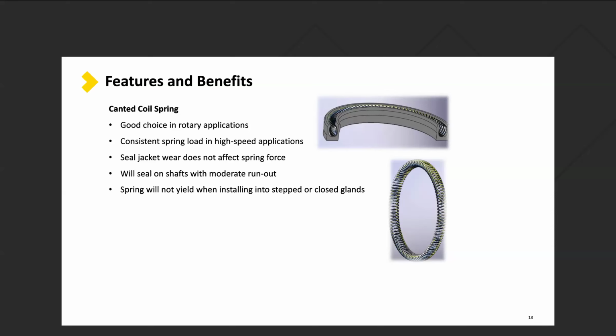It also is good for installation. So installing these seals into solid glands can sometimes be difficult. You can do it, especially if the seals are a little bit larger. When you get to smaller seals, you can damage the springs installing them into solid glands. Since the coils butt and the spring doesn't yield when it's over compressed, you can sometimes get away with installing these a little bit better into solid glands than you could with V spring or helical spring.